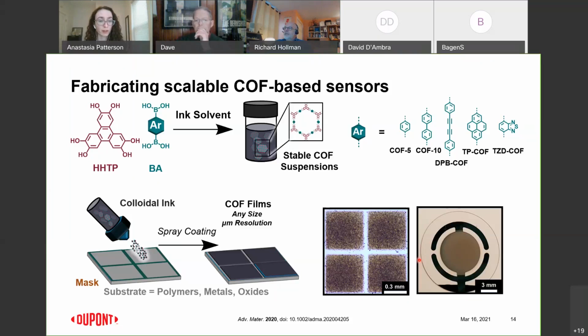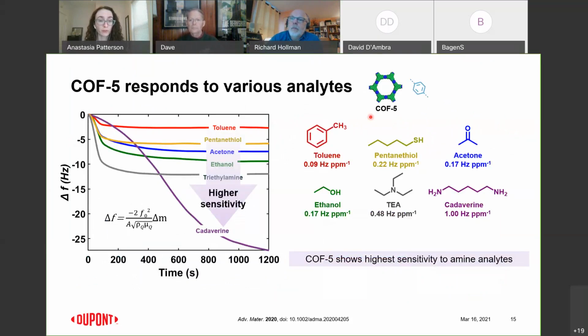All right, so the first set of data I'll be showing you is based off of this material, COF-5. It is the smallest linker and the simplest to start with. COF-5 was spray coated, creating a film, and then dosed with all the analytes listed on the right side of the slide. On the left side, you see that delta frequency versus time curve that I was cartooning earlier. In most cases, as the gas is added to the system, there's some equilibration period, and then about 75 seconds in, there's a leveling off of the frequency change. This is all the mass that's going to be added, and everything's in equilibration at this point.